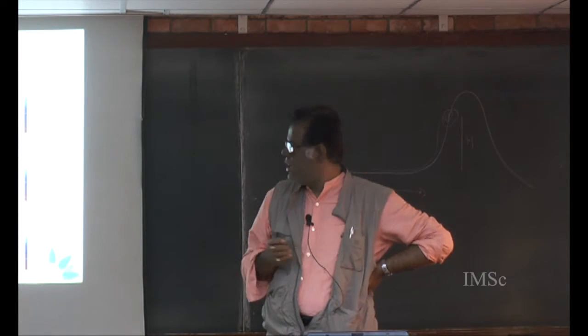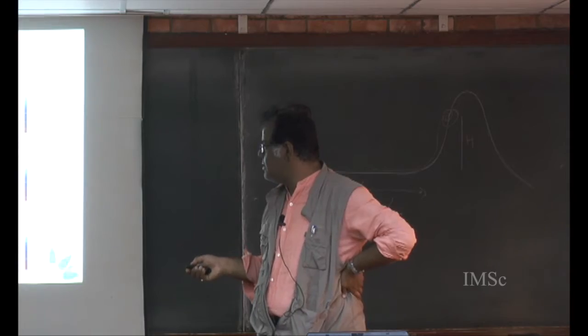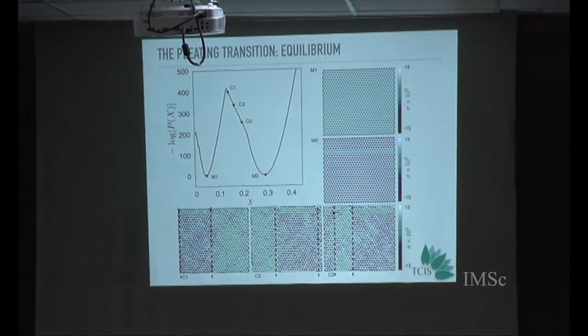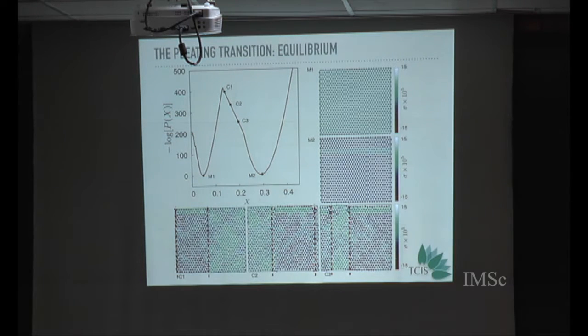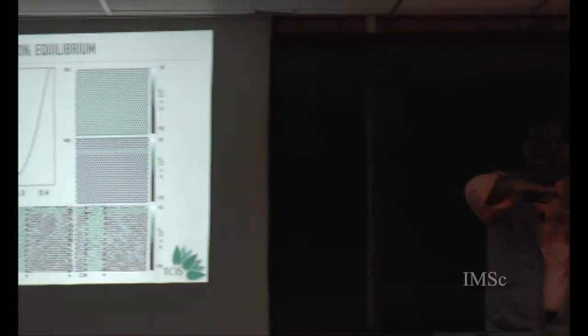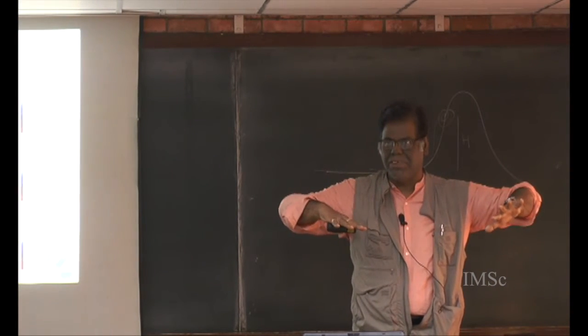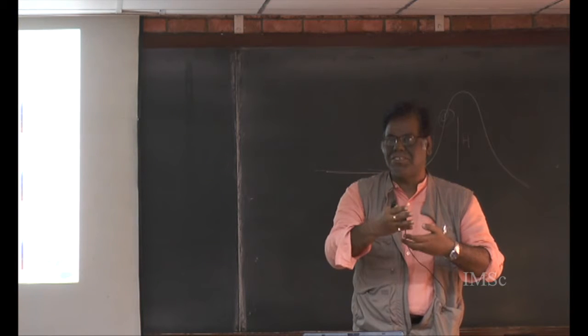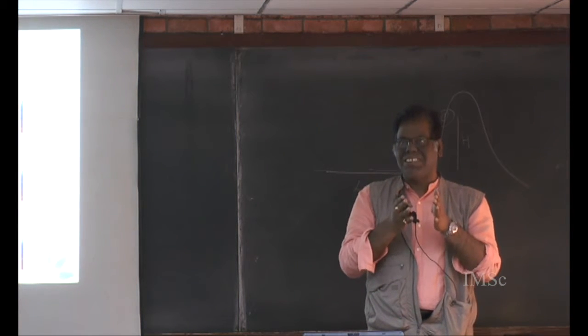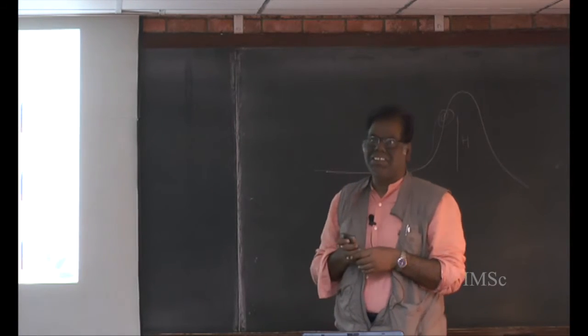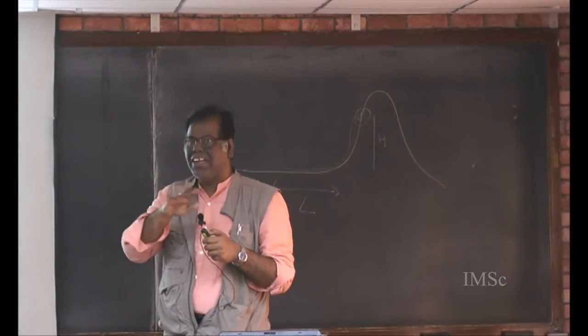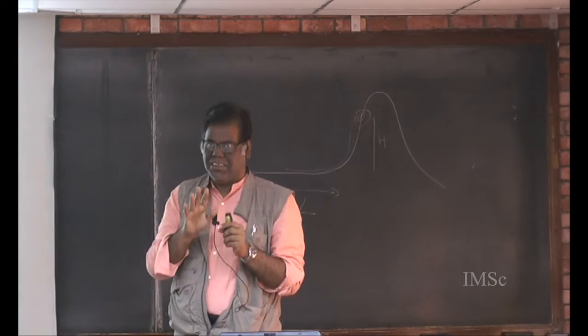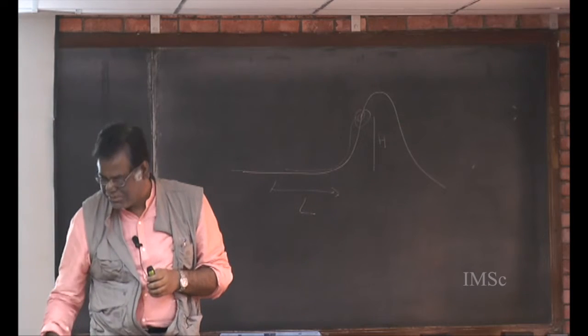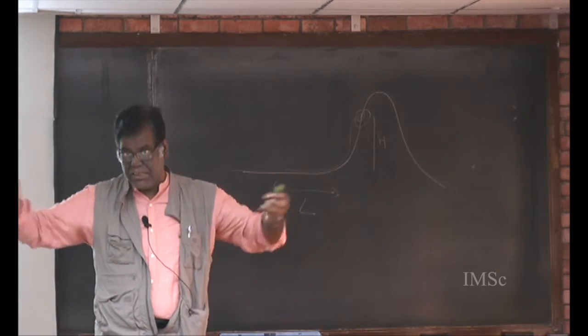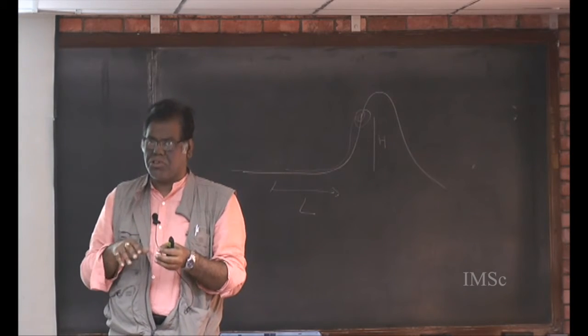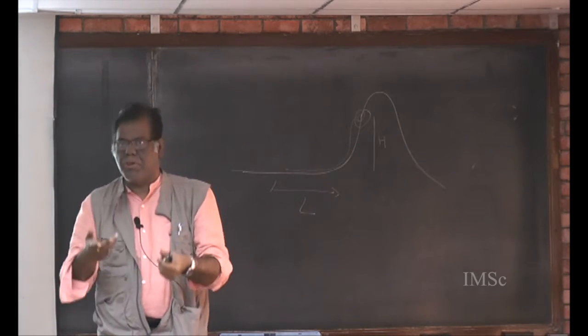What I would say is that if my system size is smaller than this, we don't even see pleats. And there's a reason for that. Because when you pleat, you also strain the other parts of the system. And if your system size is too small, then the strain energy is too large. So for a very small, stiff crystal, you would not see this transition. So there's a systematics of system size which I am not talking about here. Yeah, I agree with you on this. And as you increase the size, different configurations which were not possible in the smaller systems will become possible.